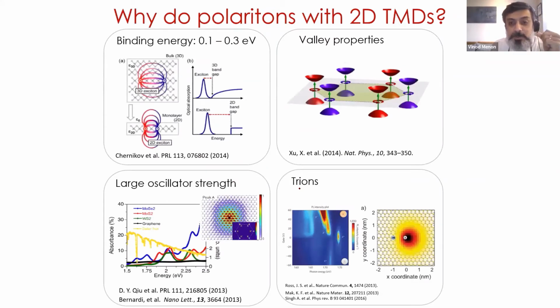So just to quickly summarize the reasons why one would want to do polaritons with 2D materials: the binding energy, the large oscillator strength. Because the binding energies are large, you can even get charge complexes called trions, which exist in these materials. You can also get valley properties, which is the fact that you can come with circularly polarized light and excite carriers with specific spin states. I'll talk about that in a few slides.